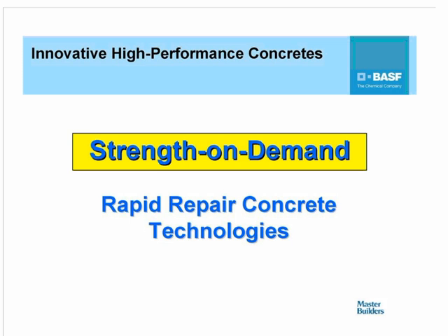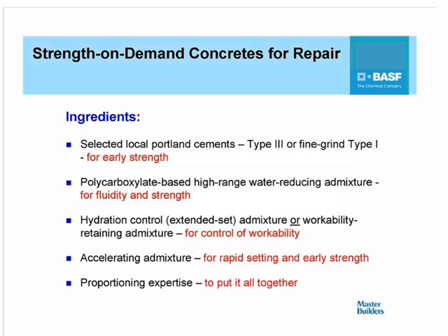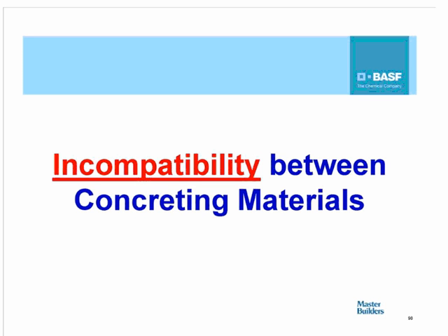Admixtures are also being used in innovative high-performance concrete applications, such as what we call the strength on demand. These are concrete mixes that can yield very high strength shortly after placement, typically within 3 to 4 hours after placement. And as a result of that, they lend themselves very well for use in replacing deteriorated sections of concrete pavements, or also in other industrial facilities. But again, it's the system of admixtures and the use of these admixtures that allows these to take place.